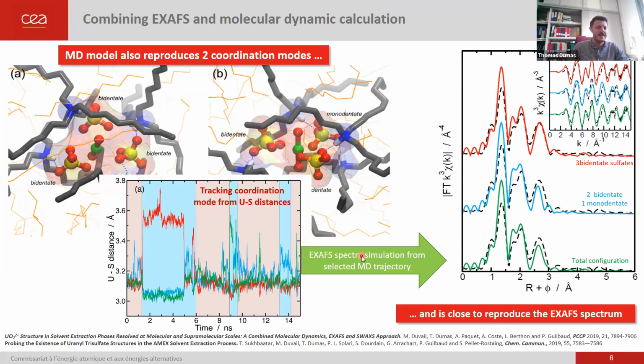and then you can make an EXAFS spectrum out of it. And this is what Magali did, and we can select either the blue part or the red part or the total calculation to make EXAFS spectra. And as you can see, it works quite well, and you can compare it to the actual experimental data. So it closely reproduces the EXAFS spectrum. You can see that the three bidentate sulfate looks to be better than the other. And this is a fine tuning of the molecular dynamics model. So now the thing is going back to the model people who can tune their model to reproduce better the experimental data.